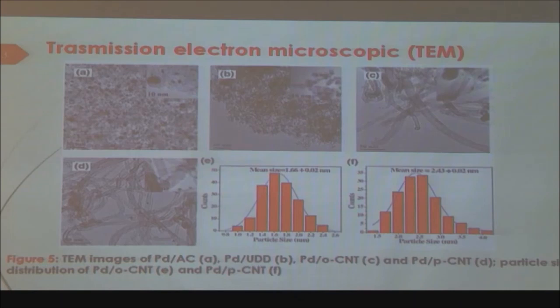So in order to keep the process simple, we use molecular hydrogen for the reduction process, and we just take a palladium salt, palladium nitrate or palladium chloride, in a very little amount. We do not need an excess of it. For example, if you have 100 milligram of your carbon material, even 2 to 3 milligram of your salt is enough for doing the reaction. So see how low an amount of metal you require. So you adsorb it, you make the catalyst, and then we